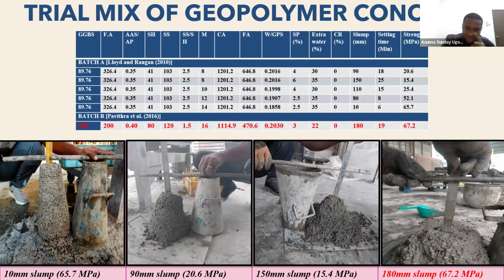That being said, I wanted to throw a bit more light on this because, in my case, this table you see here took me about 5 months in my trial mix. What was causing the error was not the mix parameters I used, but the mixing method, the mix design procedure that I used. So it is important that you take note of this mix design procedure.